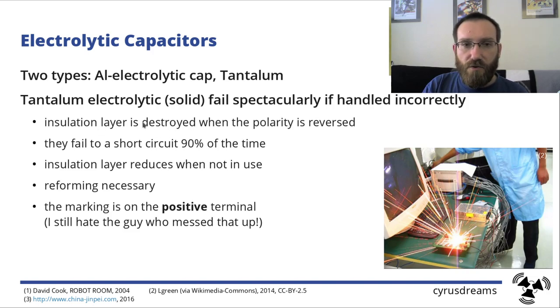But if you destroy the insulation layer, they will short out 90% of the time. They will go to a hard short and it can carry several amps. And that happens if you reverse the polarity by mistake. And it's the same deal with the tantalums. They reduce the insulation layer when not in use, so you should also reform them, putting them onto the intended voltage for 5 minutes, 20 minutes, something like that.